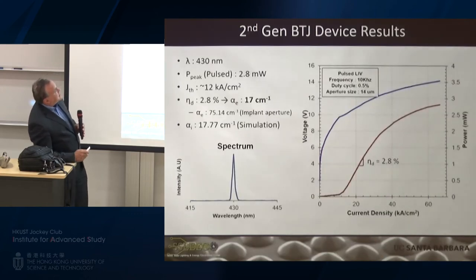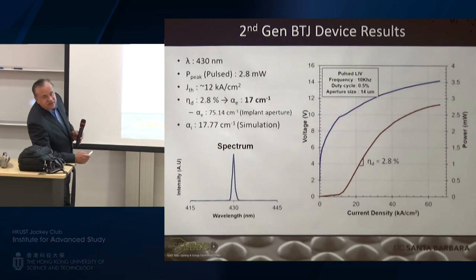What we improved in the second generation with the buried tunnel junction devices is basically going to higher doping. We now get to 12 kiloamps per square centimeter. We got the loss down. However, you'll notice VCSELs are still not very good, because the loss is actually quite huge, 17 inverse centimeter. This is still quite a bit higher than our edge-emitting lasers. Gallium arsenide VCSELs today are 1 inverse centimeter. When we get down to that range, then you'll start seeing some serious power.